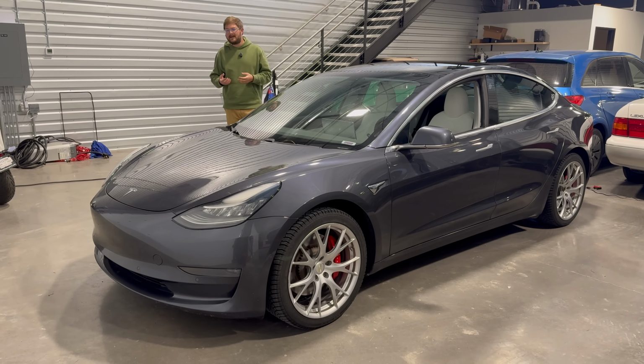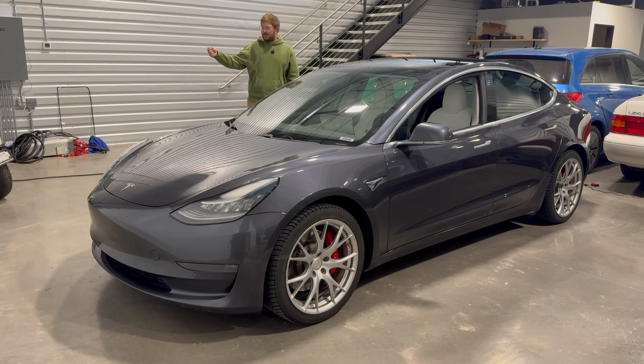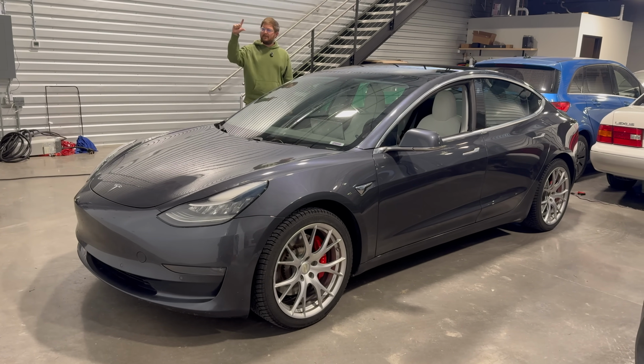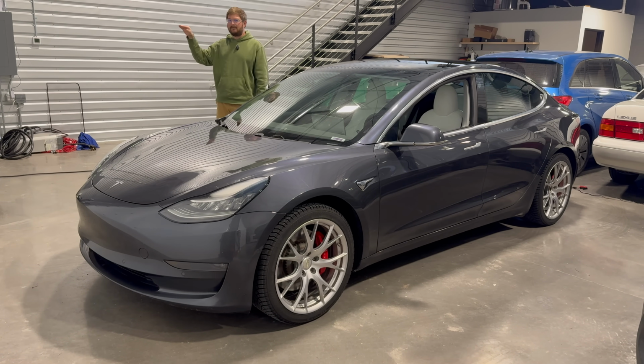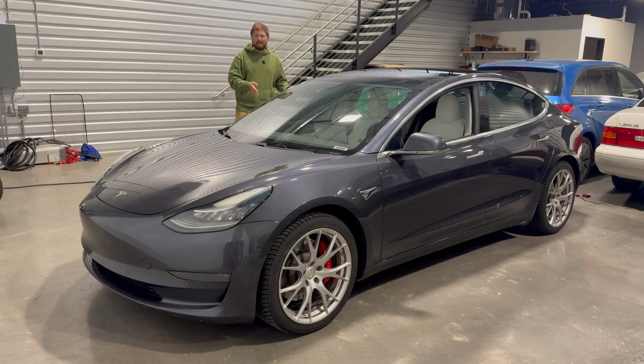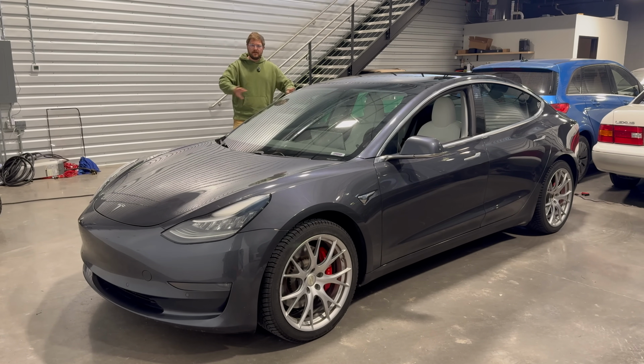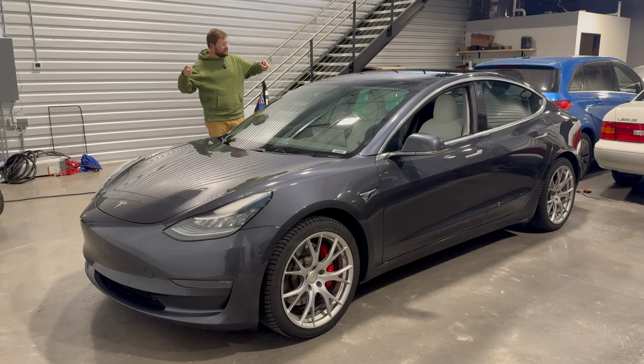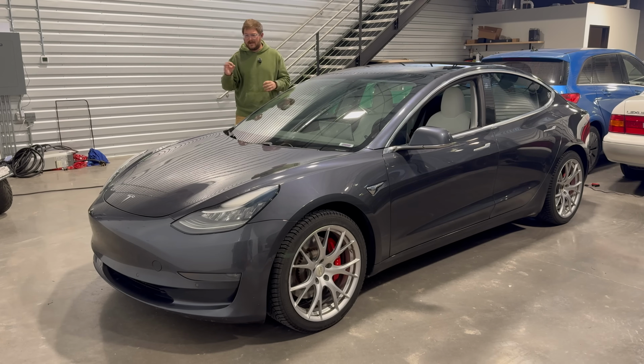And from a user perspective, typically something I always do whenever we buy a new car is I'll charge it to full, we'll drain it to dead, typically at 70 miles an hour because we tie it into a range test. We look at how many kilowatt hours we pulled out of the battery pack during that test, and that's a great starting point. And then whenever we want to measure capacity later on into the future, we would do the same thing. You charge it to full, you drive gently to reduce heat loss all the way till the car stops moving, use all the buffers, account for any BMS sway from when voltage clicks off up top to when voltage clicks off on the bottom, and then you can see how many kilowatt hours you pulled, and that's your reading.